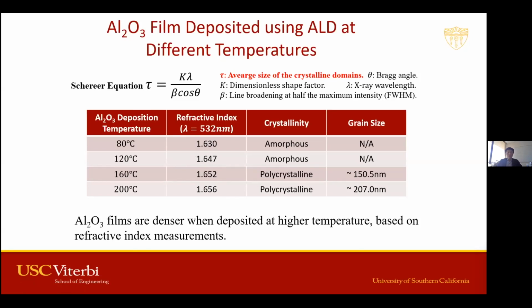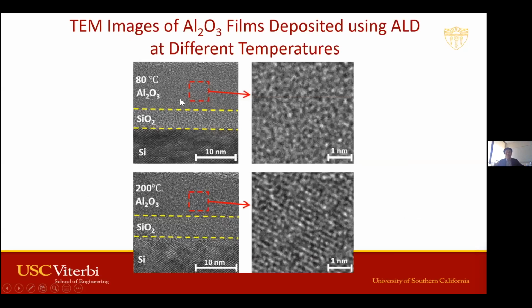Without going through much detail, let's just look at the TEM images. Here is the TEM image of the aluminum oxide layer deposited at 80 degrees C. This is the zoom-in view, and you can see it's amorphous. And here is the aluminum oxide layer deposited at 200 degrees C, and you can see it's polycrystalline. You can see the crystal structure here.